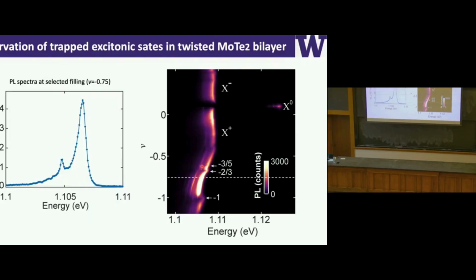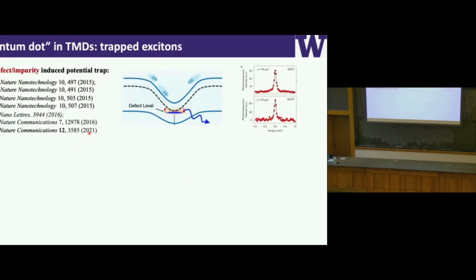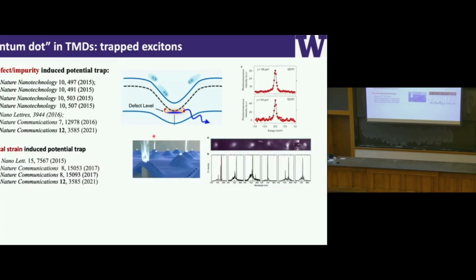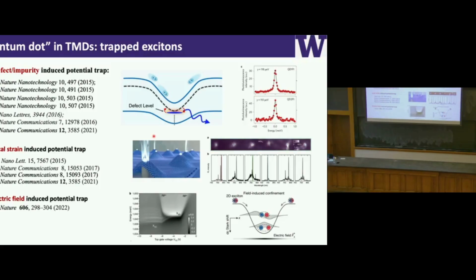First, let me take a line cut of this feature and look at the spectra. Here's the luminescence, taken at filling factor about 0.8. We see a main free trion feature with line width about 1 millielectron volt, and I also have a narrow feature sitting on the shoulder with line width about 200 micro eV. In the community, we know this narrow feature comes from trapped excitonic states, as has been demonstrated in many different examples. These trap potentials can be provided by defect impurities, by local strain, or by electric field. In my case, I don't know exactly the origin of the traps.